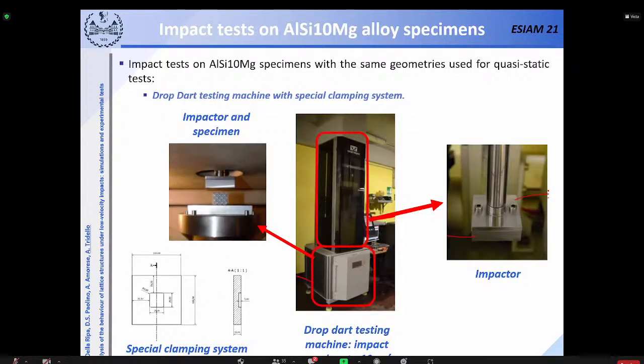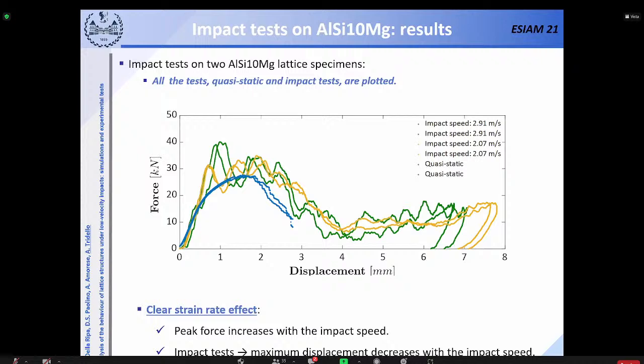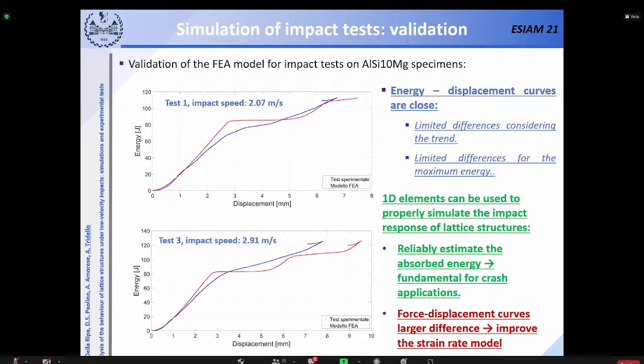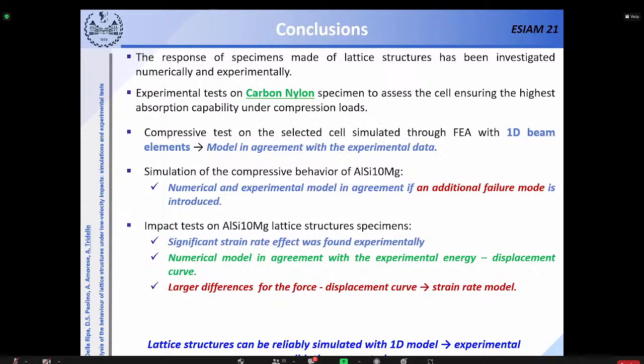Then we ran impact tests on AlSi10Mg specimens, and we found that a significant strain rate effect was present, and this had to be also modeled to rightly predict the maximum impact absorbed energy. Indeed, the final results were quite good in terms of final values of absorbed energy, but the shape of the curves is not so in agreement. This is why further development are necessary for the model to rightly predict what happens with AlSi10Mg alloys, metallic alloys. And this is the further development.